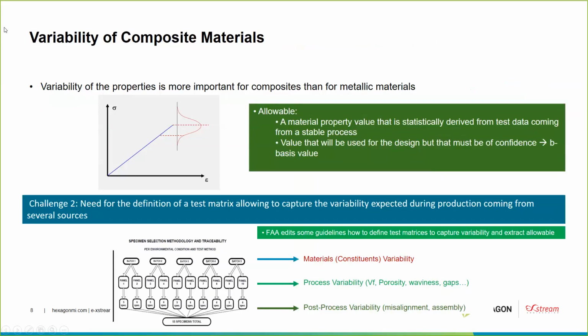Then we have another challenge when we use composite material. If I replicate 5 times, 10 times the coupon that I've just used before, I will never get 10 times exactly the same final strength. Unlike metallic material, what we observe with composite is a larger distribution of the final strength. This raises the need to use what we call the allowable material, which is a material property that is statistically derived from test data coming from a stable process. And this value, which will be used for the design, must be a value of confidence. So that's why we give the possibility to generate a B-basis value to take into account this distribution of final strength of the coupon.